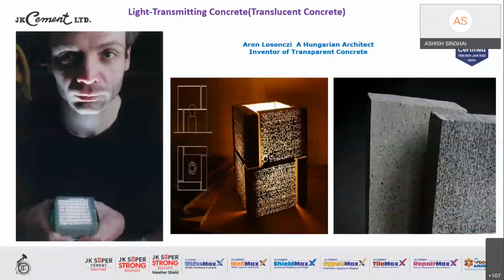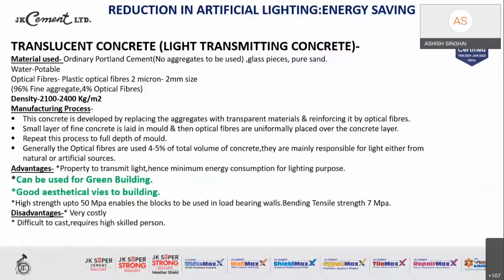What he has done, he has used 96% of the fine aggregate and inserted optical fibers to the extent of 4%, and plus some good quality additives, fillers, and polymers. By combining all these things, he prepared one concrete where deliberately no coarse aggregate was being used. 96% was fine aggregate and 4% optical fiber plus good quality aggregate, fillers, and chemicals. By using that, the density that he could achieve was about 2,100 to 2,400 kg per cubic meter.